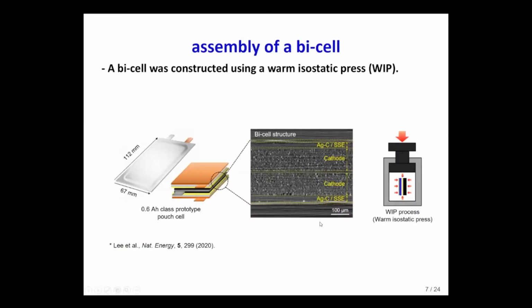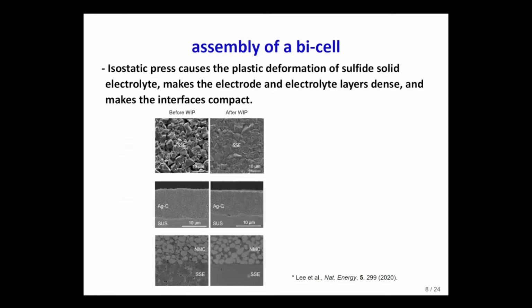We prepared a bicell with this design. We laminated a double-sided cathode, 2 solid electrolyte layers, 2 silver carbon composite layers, and 2 stainless steel foils. Then the assembly was pressed with a warm isostatic press. After the isostatic press, the cathode becomes very compact and the void spaces in the electrolyte layer almost disappeared. The sulfide-based electrolyte undergoes plastic deformation during this process, and consequently, the grain boundary resistances and other interfacial resistances are going to be minimized.